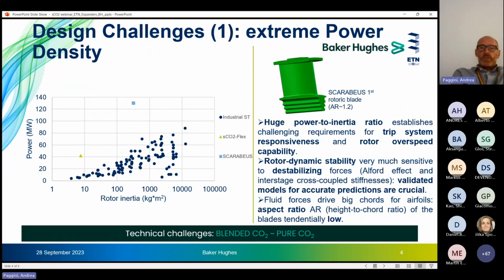Which are the challenges? One immediate criticality is that in case of loss of load, so essentially an event of a generator breaker opening, for example, or even worse, in case it's applicable, loss of load and inertia, so a coupling failure scenario, the overshoot speed reached by the rotor is well above the typical values encountered in steam turbine trains as a result of the large power density. And so it establishes very challenging requirements for the responsiveness of the trip system and for the overshoot capability of the rotor.